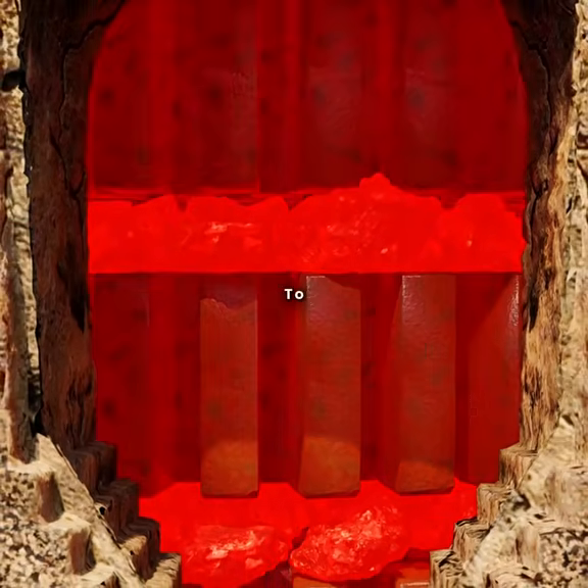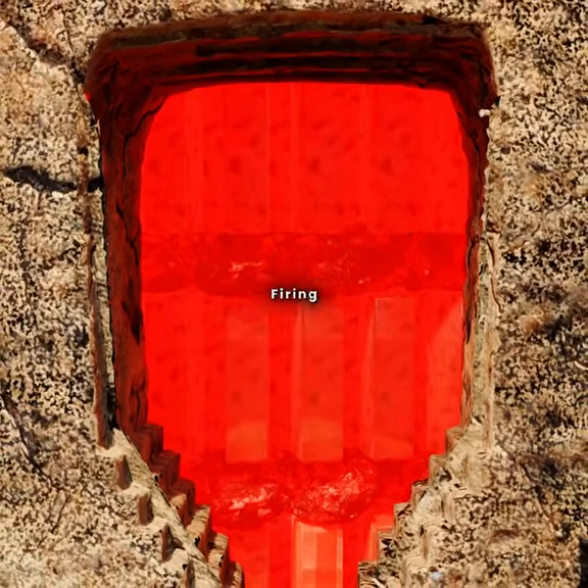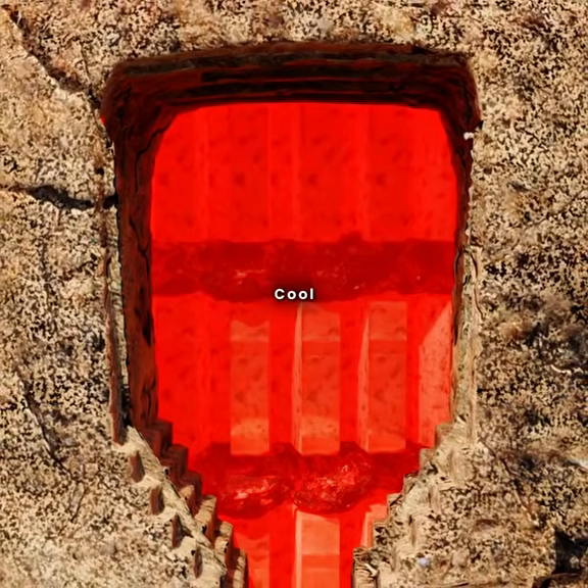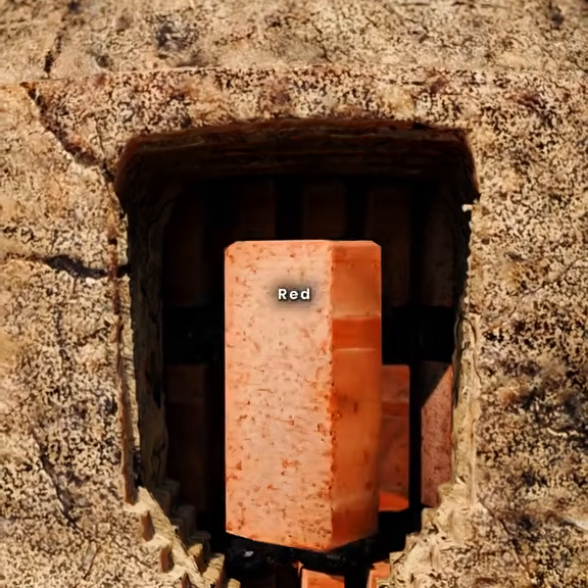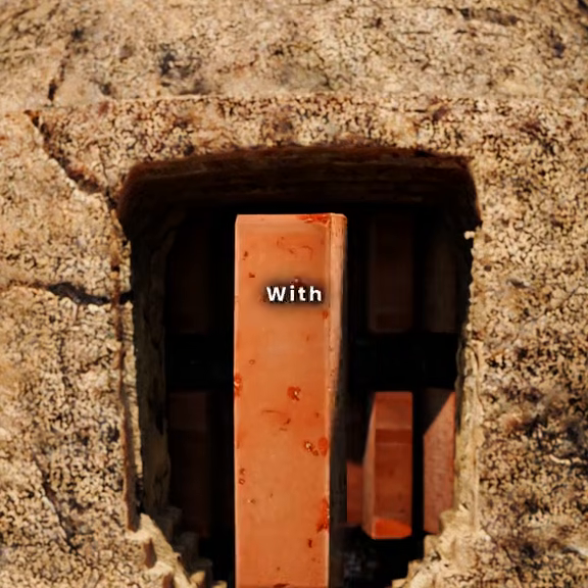Inside, temperatures soar to around 1000 degrees Celsius. Over the course of 3 to 5 days, the iron naturally present in the clay fully oxidizes into ferric oxide. When the firing process ends, and the bricks cool naturally, they emerge as classic red bricks, warm red in color and filled with tiny pores.